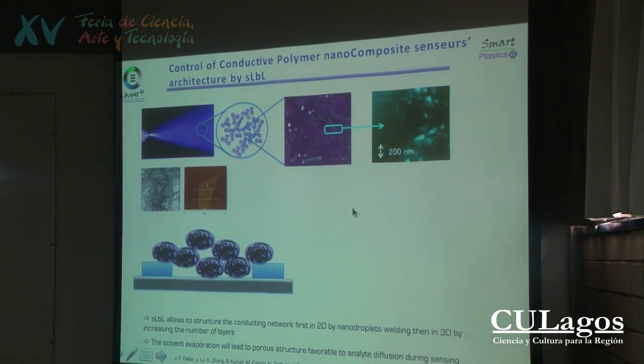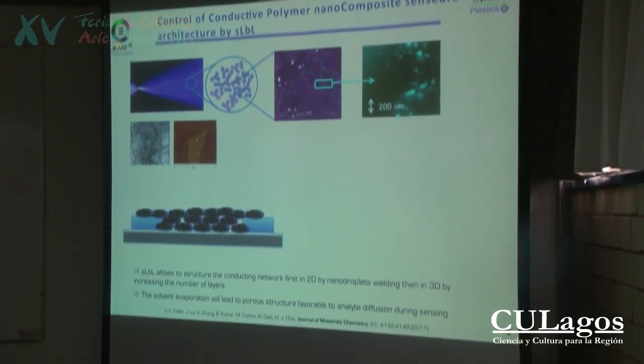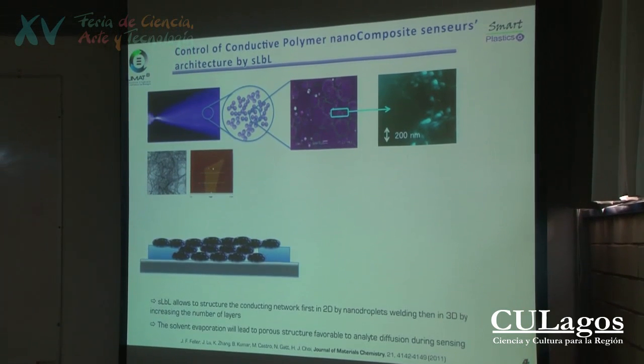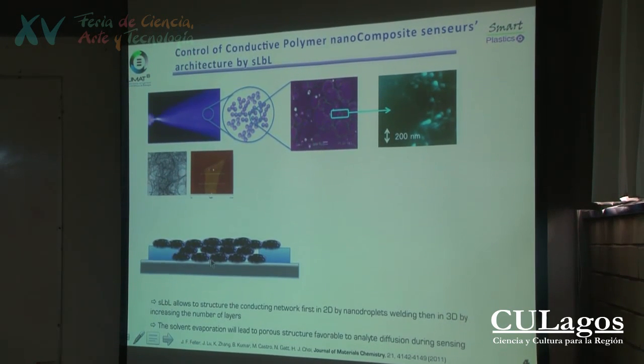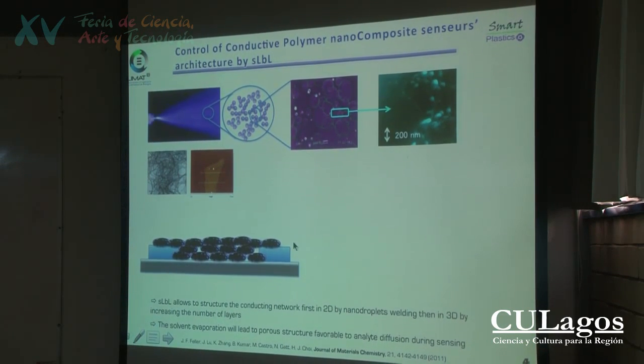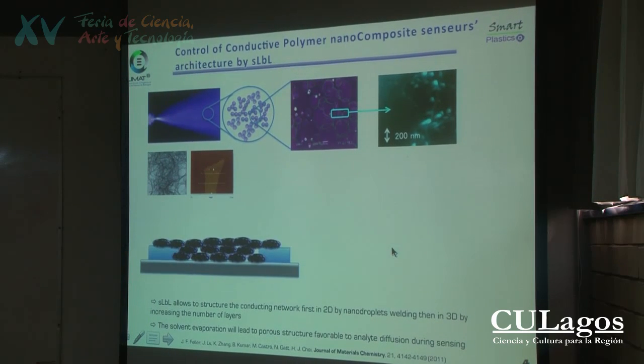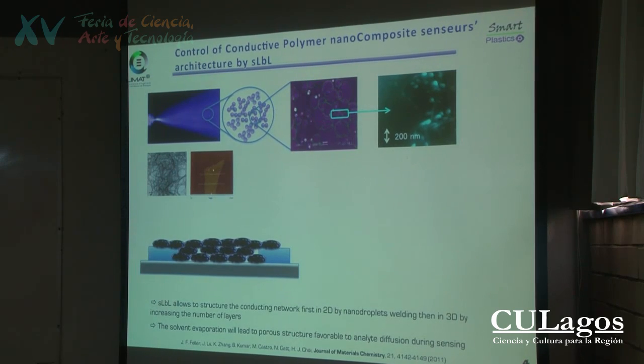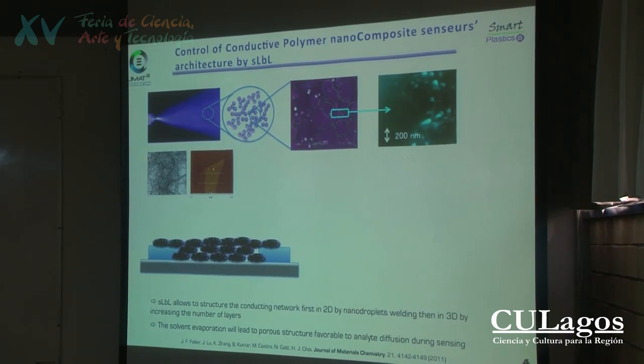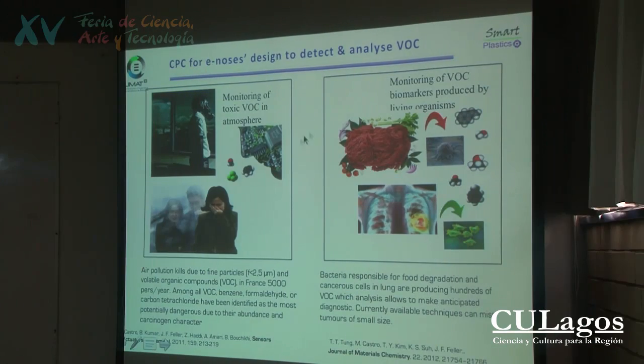And moreover, you can also control the fabrication by the number of spray layers that you will put on the electrodes to make the sensors. So here I can adjust the layers, which are very thin, about 40 nanometers thin, each layer. And I can build the 3 dimension like this. Such kind of sensors have been fabricated. It's possible to use them to monitor the atmosphere.